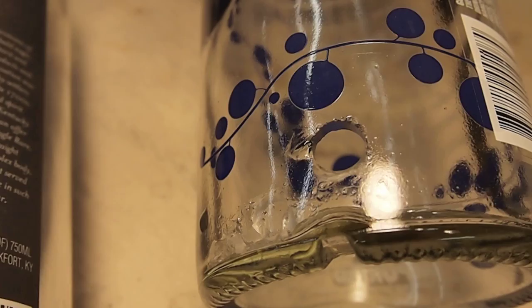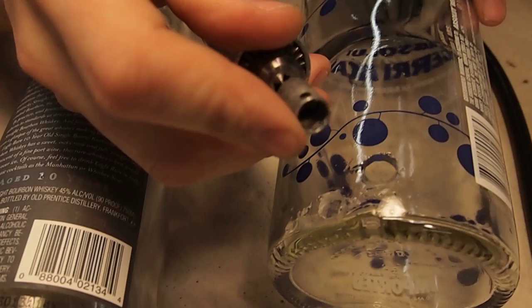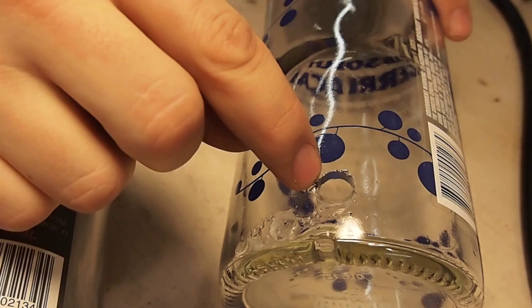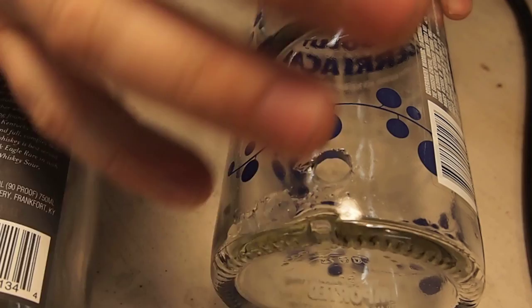And also we filled it up with water first. Why did we do that? So, glass is a really good thermal insulator and if you're using a friction bit like this, all that energy gets turned into heat. Now, because it's a good insulator, the area region right around the hole where we're drilling is going to heat up and want to expand. As opposed to the area just outside of that which stays cool. So it's expanding at a different rate.